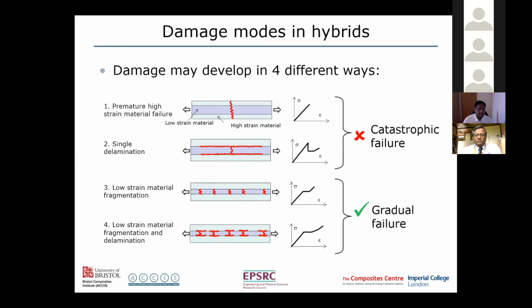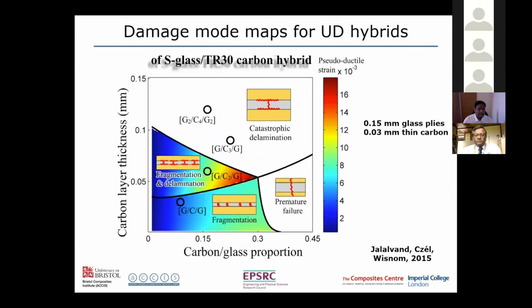So what does this depend on? So we developed these damage mode maps, which show how the different combinations of materials create the pseudo-ductility and the right failure mode that we want. So it really depends on two parameters. In this case here, I'm showing this for a S-glass and high-strength carbon combination, but we can produce these maps for any material combination. And you can see on the bottom axis, we've got the carbon-glass proportion. And the second axis is the absolute thickness of the carbon layer.